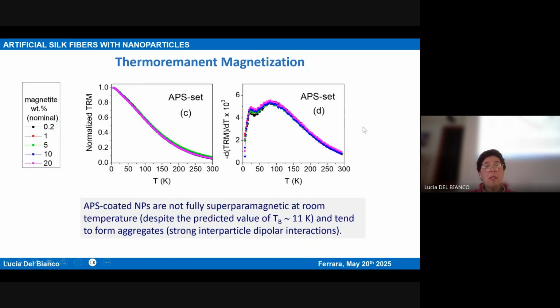Let's see how different is the behavior of the fiber with the APS-coated nanoparticles, the ones that gave the worst results in terms of magnetite loaded in the fiber. In this case, it's a very incredible behavior, because all the curves, irrespective of the magnetite content, are superposed. And the remanent magnetization is not zero at room temperature, which means that actually not all the nanoparticles are in the superparamagnetic regime.